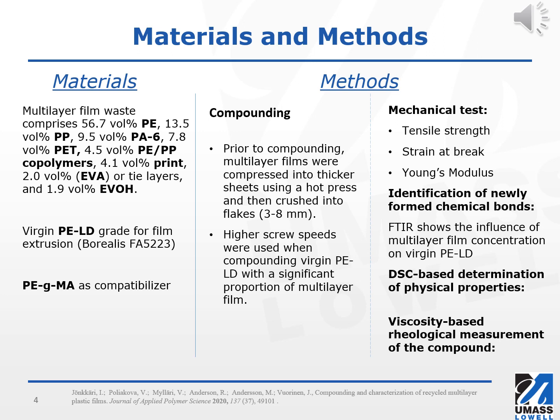In the steps that came before the compounding processes, multilayer films were first compressed into thicker sheets using a hot press and then crushed into flakes. When the virgin LDPE was combined with a substantial percentage of multilayer films, higher screw speeds were utilized in the compounding process. The tensile strength, strain at break, and Young's modulus were the three metrics that were used to characterize